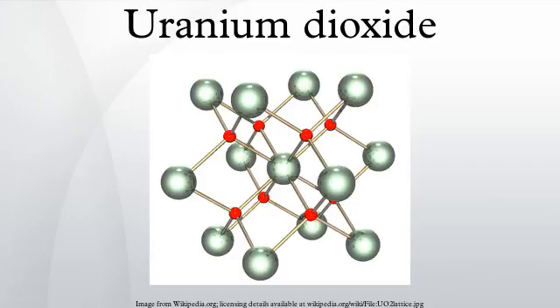Uranium dioxide is produced by reducing uranium trioxide with hydrogen. UO3 plus H2 yields UO2 plus H2O at 700 degrees Celsius. This reaction plays an important part in the creation of nuclear fuel through nuclear reprocessing and uranium enrichment.